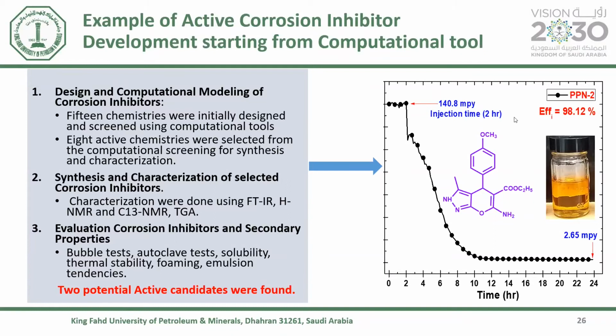The initial corrosion rate was 140 MPY after 2 hours. And after 24 hours, the corrosion rate was reduced to 2.65, which was a very, very good result. So this is one of the examples where we've used this tool, and it helps us to reduce time and effort in the lab, because testing in the lab involves a lot of standards and a lot of equipment. So by using this tool, it cuts a lot of time and equipment.